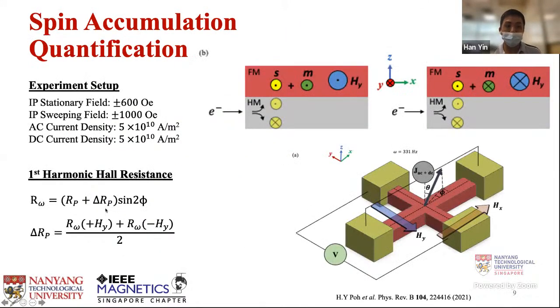So when we apply a positive Hy field, we obtain a result of RP plus delta RP. Then when we apply a negative field, we also obtain a result of RP minus delta RP. But the RP in the positive and negative fields should be the same, just in the opposite direction. So that's why if we sum these two terms together, we can cancel RP and isolate delta RP by itself.